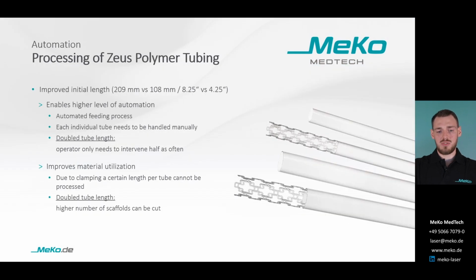As we have seen, the material uniformity has a direct impact on the laser cutting accuracy and in the end on the BRS quality. However, another important factor in the production of a BRS is economic efficiency. This is mainly determined by the material utilization, the yield of good parts, and the laser cutting efficiency. To illustrate this, let's have a look at the Zeus Absorv XSE, which is roughly twice as long as tubes of previous generations. And this longer length enables a higher level of automation because the laser machine is loaded manually for each tube, and then the laser automatically cuts a certain number of scaffolds until the material is used. This means for a doubled tube length, the operator needs to intervene half as often.